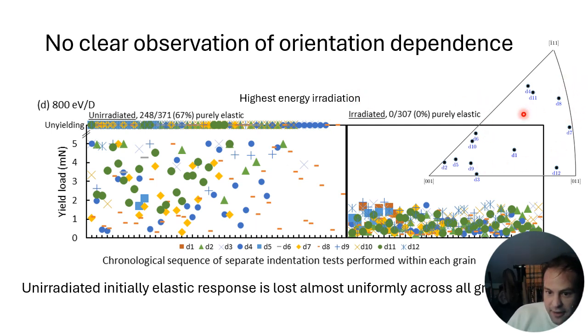But across these various grains that I've looked at, every single one of them seems to go from before irradiation, shown on the left side of this plot. I'm plotting the yield load. Before irradiation, most of them are perfectly elastic, shown by this break in the axis. And after irradiation, every grain, no matter which orientation, has simultaneously become yielding by 1 millinewton. So this was the highest energy.